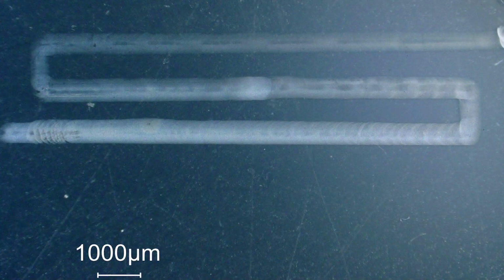With our technology, it's self-contained in a tiny nozzle that the electrolyte is flowing within. And the key there is that the electrolyte is constantly flowing, so we're reducing mass transport and really making a consistent material during the deposition or during the growth of our part or material that we're putting onto a different substrate or a different part.